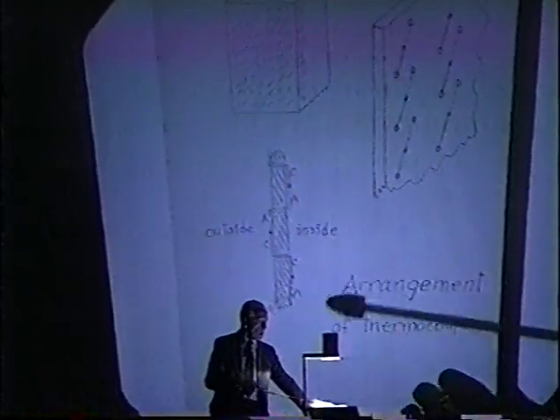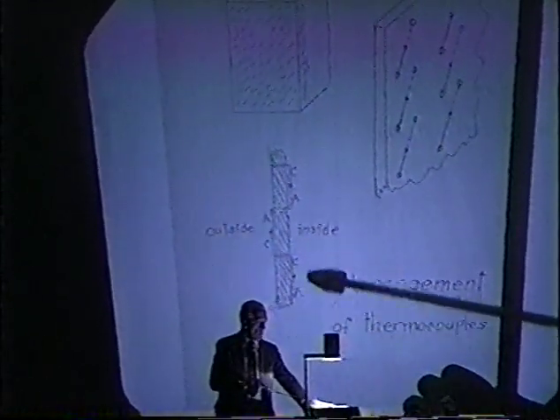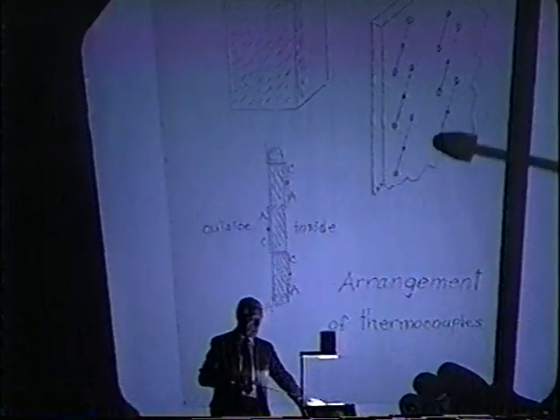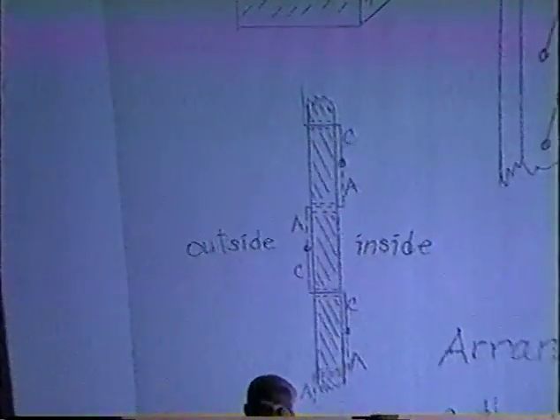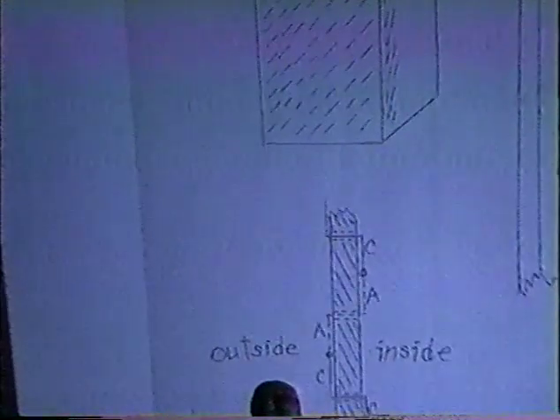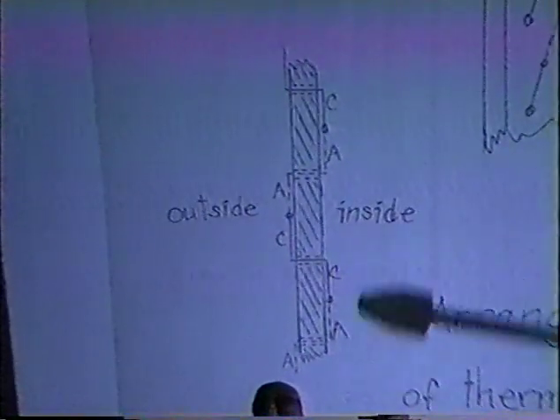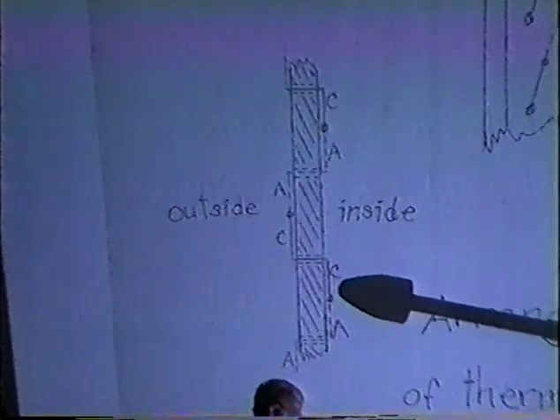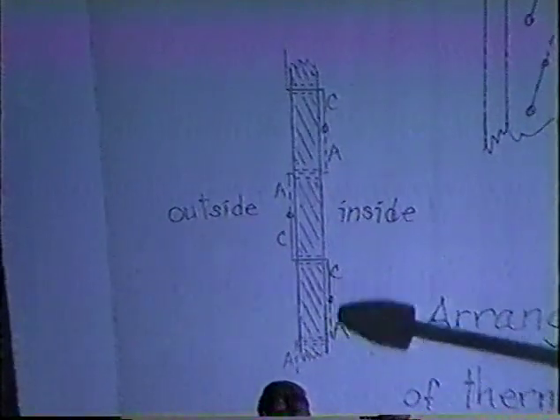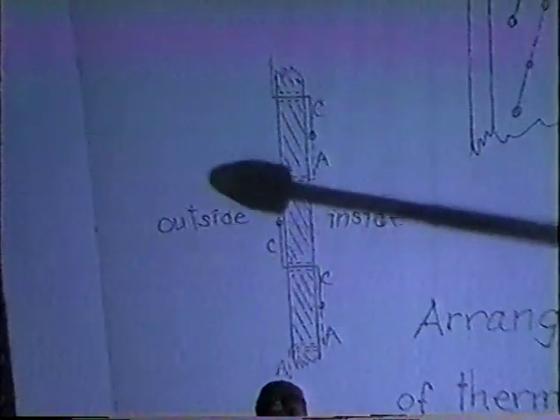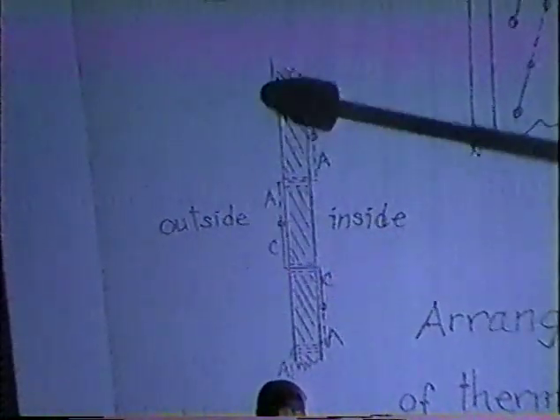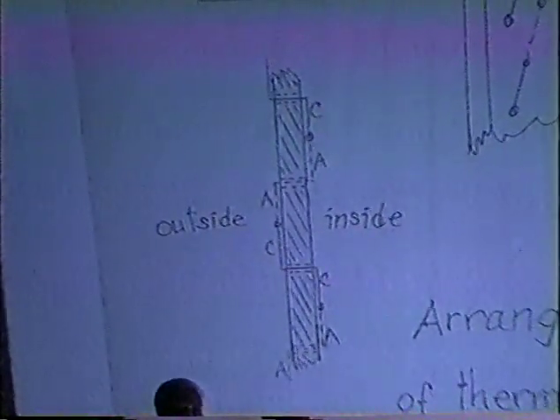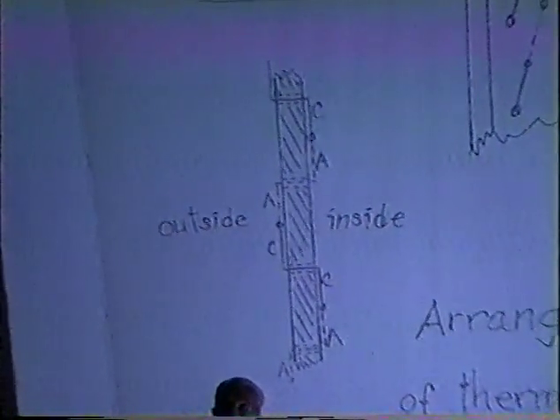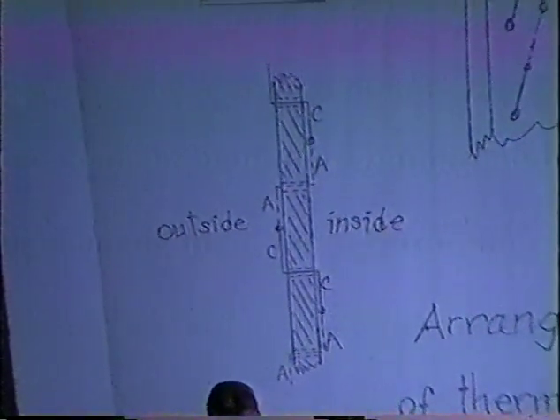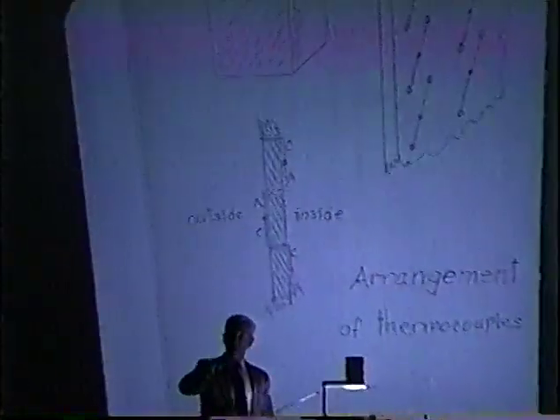The threading is done in such a way that on the inside surface of each of these walls and the top of this box, we have one polarity of the thermocouples. I symbolize that by A to C. On the outside, the opposite polarity, C to A. And therefore, these are effectively in series of opposite polarity, one after the other.